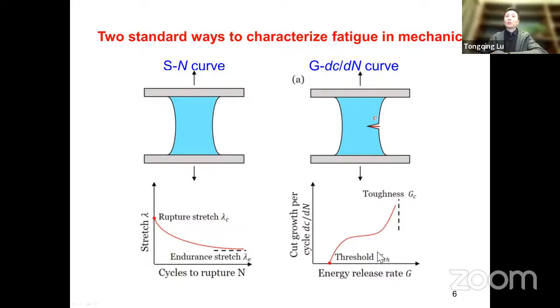And in this method, we have two material properties. One is toughness, which means if you stretch it one time, it breaks, you get a number of toughness. The number of critical energy release rate is called toughness. And another material property is called threshold, which means below this critical energy release rate, no matter how many times you apply cyclic load, the crack does not grow.